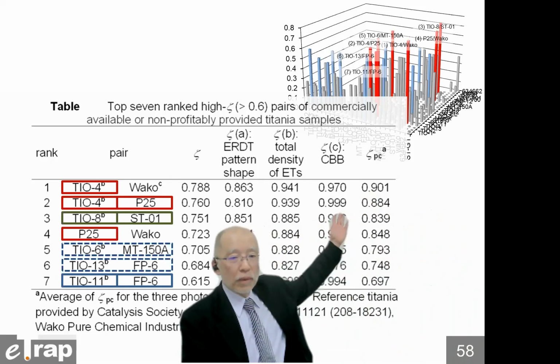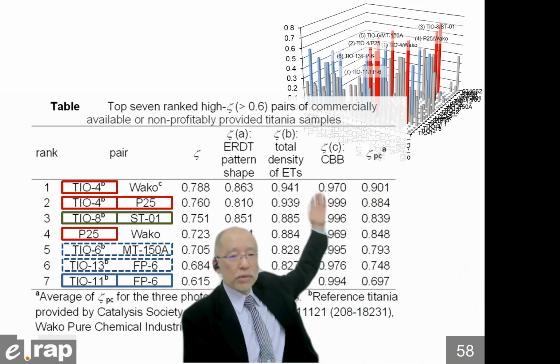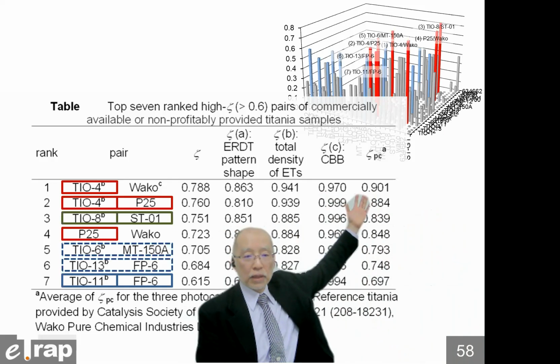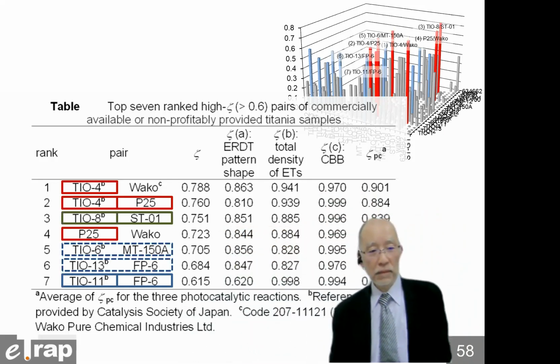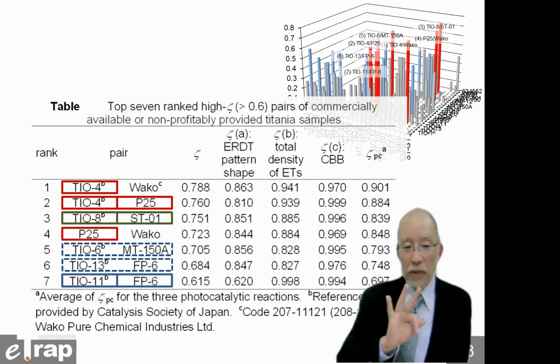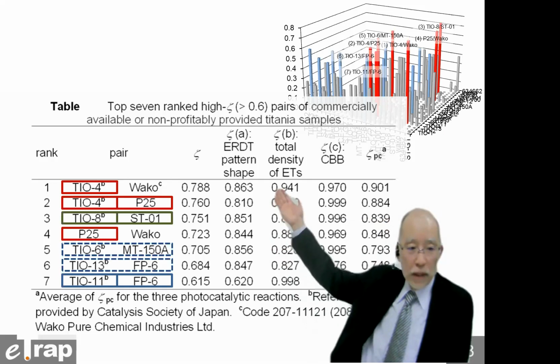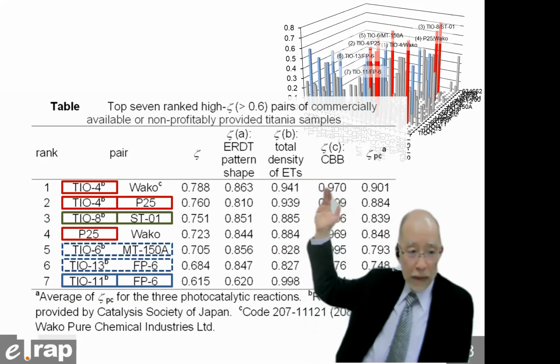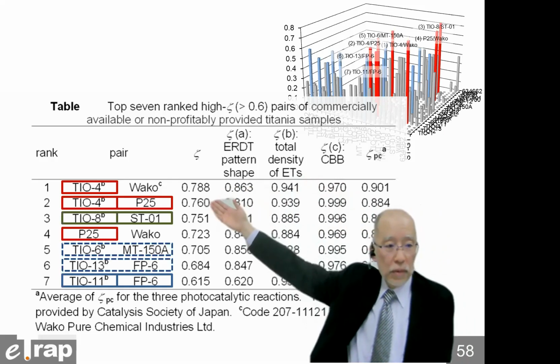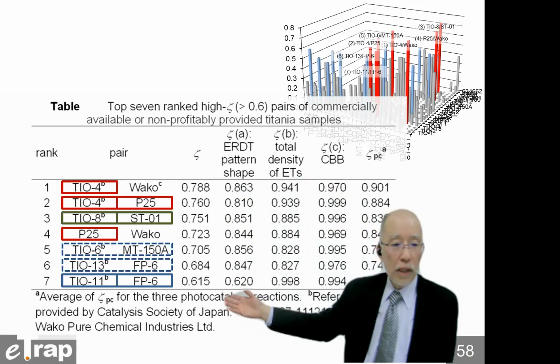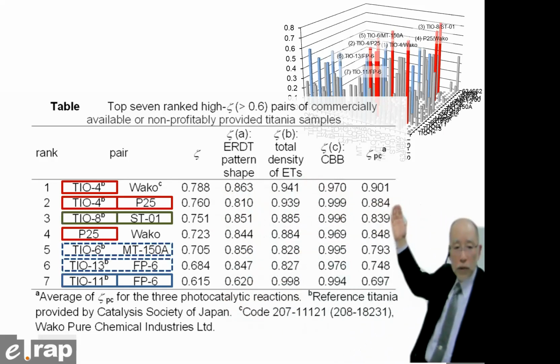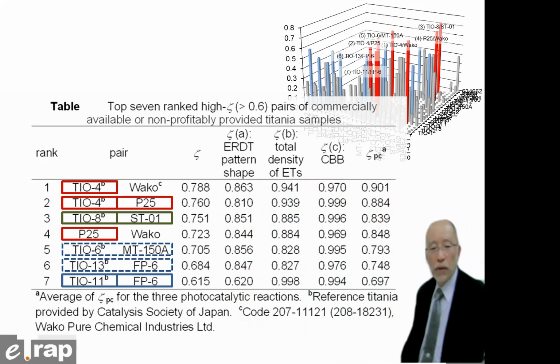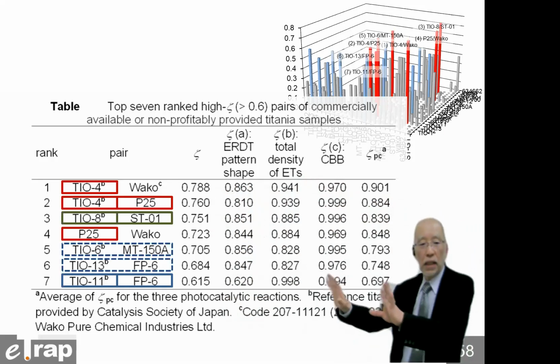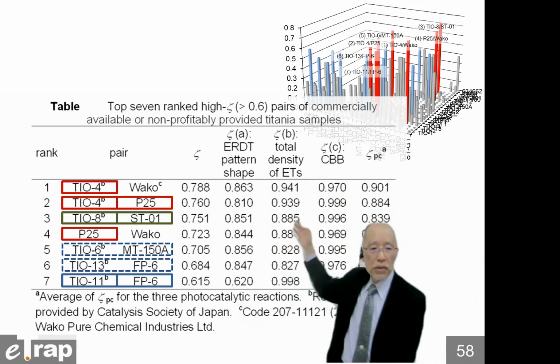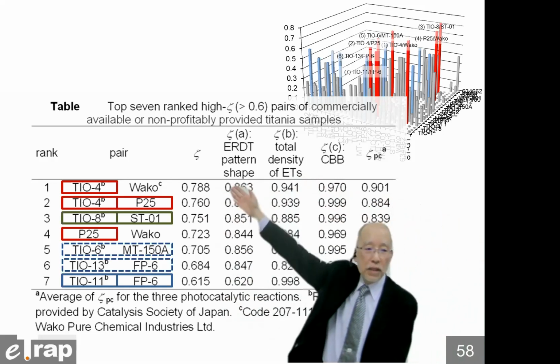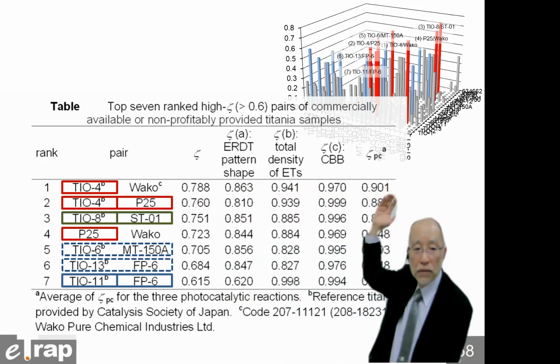And rank 1, TiO4 and Wako, gives a degree of coincidence of photocatalytic activity of higher than 0.9. That is the average of 3 reactions, 0.9. So that means TiO4 and Wako give almost the same photocatalytic activity. And with the decrease in degree of coincidence from 0.788 to 0.615, the degree of coincidence of photocatalytic activity is decreasing. So it is possible to see the relation between this zeta value and zeta PC value. So similar samples give similar photocatalytic activity.